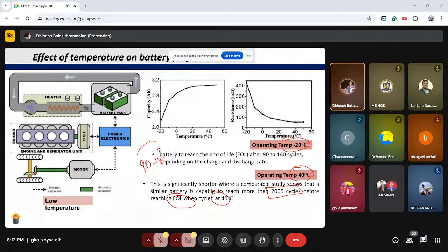So try to understand the difference. In just 90 to 140 cycles, meaning when you charge your battery 90 or 100 times, your battery would be dead. Whereas when you operate your battery at ambient or battery surface temperature close to 40 degrees Celsius, you can charge and discharge your battery 2000 times. So think about where 100 is and where 2000 is. There is a great difference in scale between these two. So we need to understand that the battery operating temperature is a key factor when you deal with it.